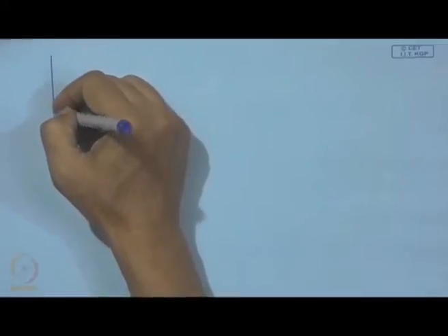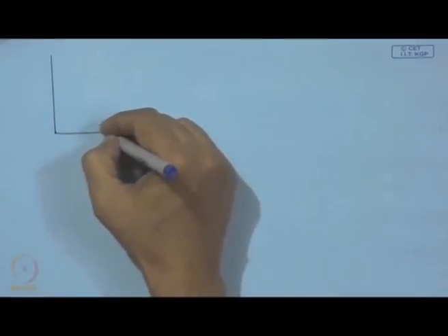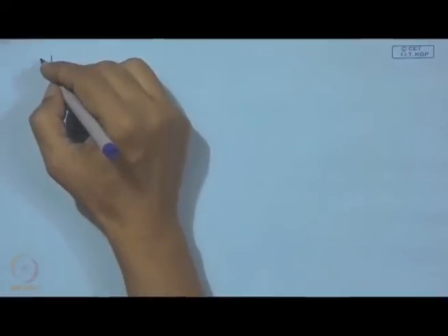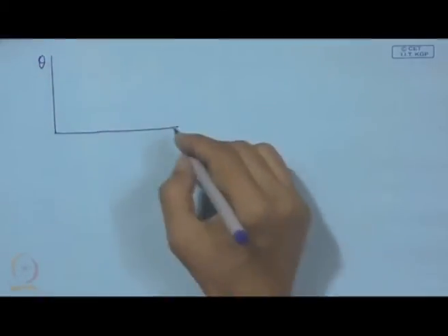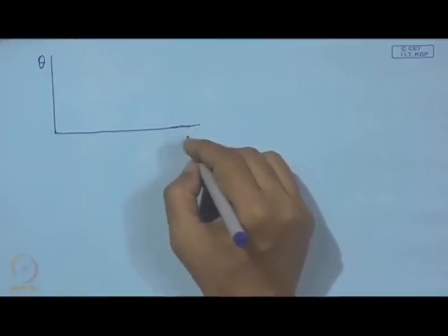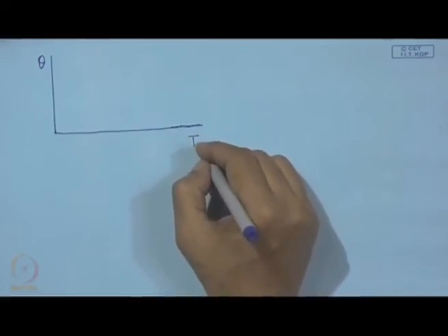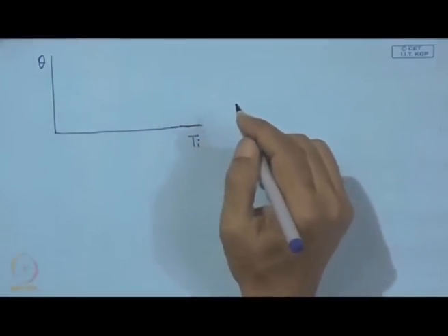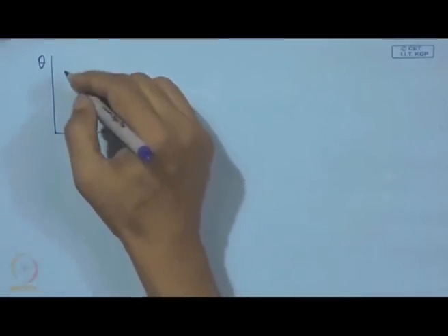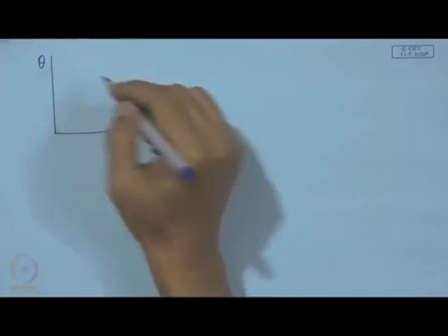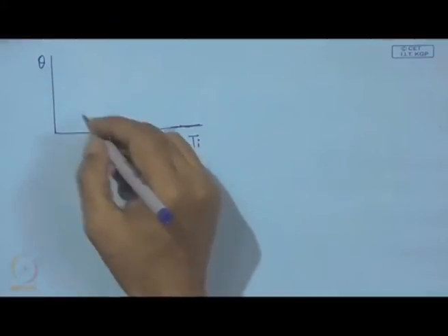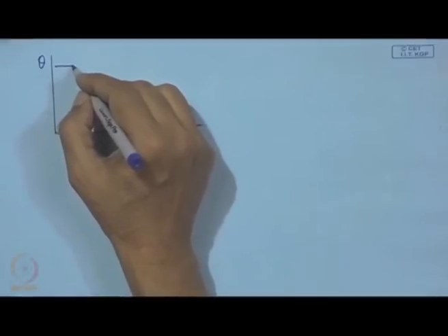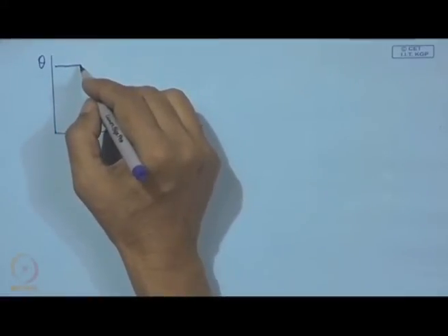And in the normal case, what we see, if this is the wetting angle and this is the percentage of titanium, then with an ordinary alloy, unless we have a certain percentage of titanium, it does not show any sign of falling theta.